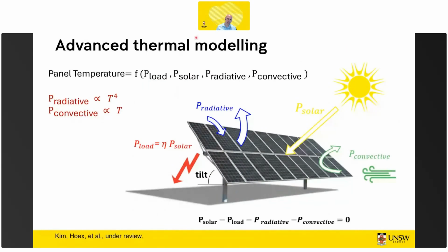And we've done a lot of developments. In the load, I will show you one example of that, but also in the radiative cooling, which in the current models that you would use in PVsyst and SolarFarmer, etc., is not as sophisticated as is actually possible. But the difference in temperatures can be 5 to 10 degrees. In terms of degradation, that means a factor of 2. So there's quite a big difference.